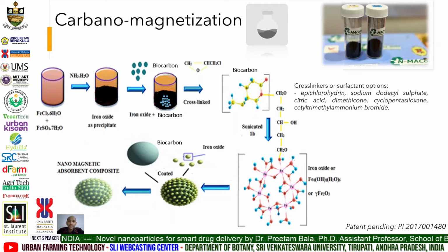Biocarbon was added in the range of 3 to 5% weight by volume and mixed completely. The suggested particle size for the biocarbon is up to 300 microns. This is also dependent on the proposed final application. Commercial activated carbon can also be used if preferred to substitute the self-prepared agrobiomass-derived biocarbon. Stabilizers are optional but preferable, especially for large volume synthesis, to prevent aggregation.